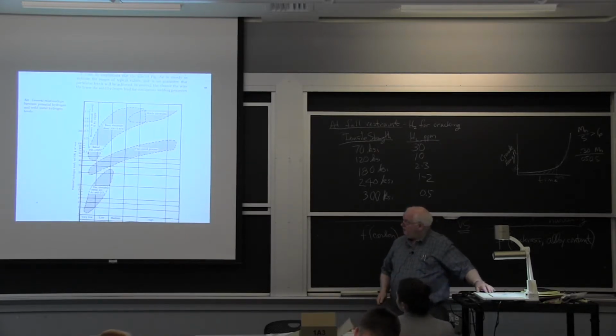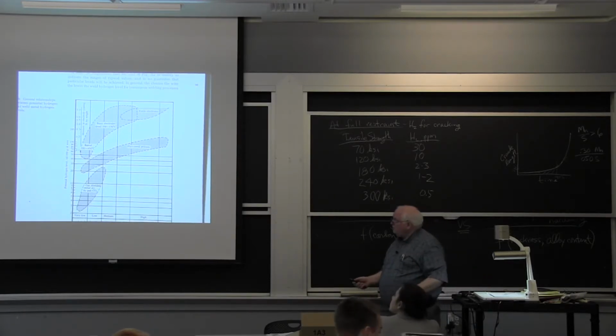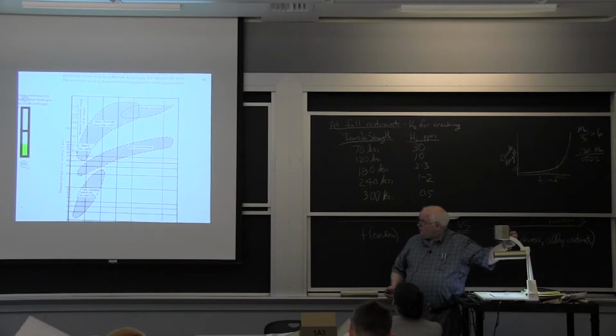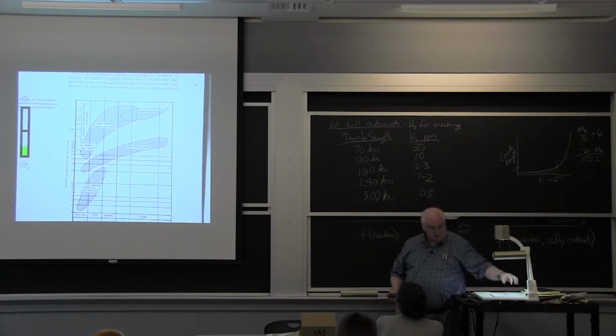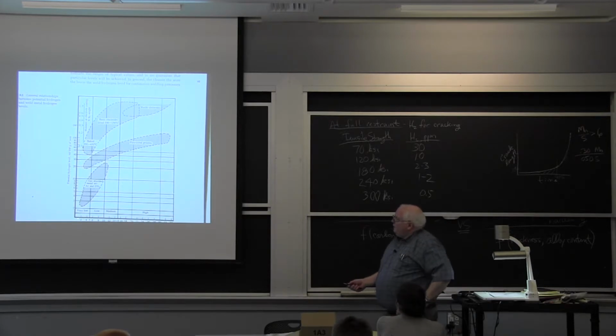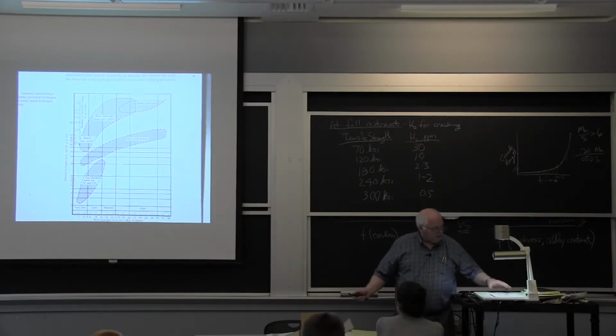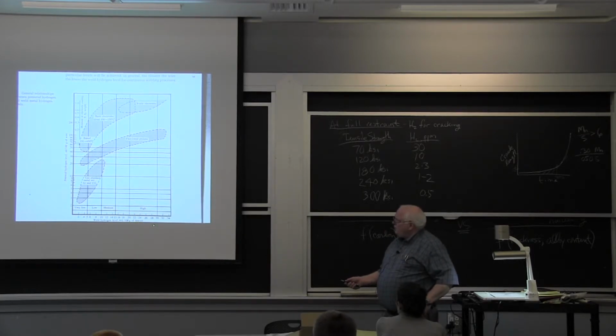There's this plot, and you'll find it in half of these books or more that I just passed around. But Frank Coe, who's probably passed away now, developed this plot in the 1970s when he wrote the first edition of the book. And he has, at the bottom, weld hydrogen milliliters per 100 grams of deposit, so you can think of this as parts per million. I told you about the highest level you might expect in the liquid is like 30 parts per million. If you use rutile electrodes, which is like a 70-14, I gotta go back and look which is rutile, but like a 70-14 electrode.